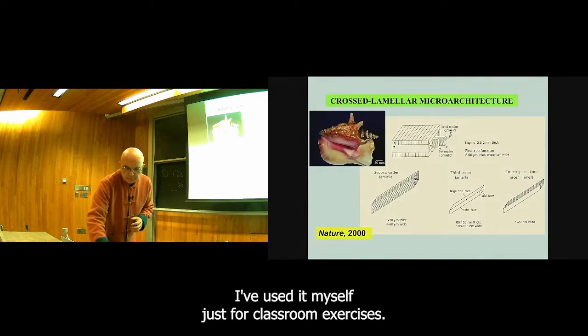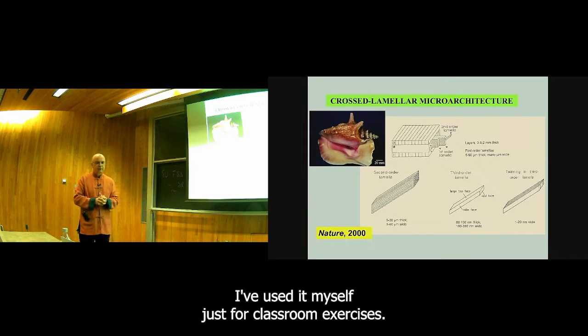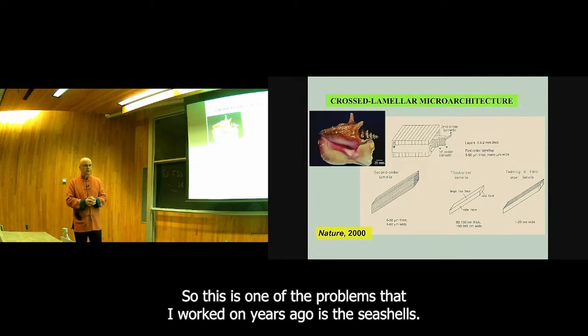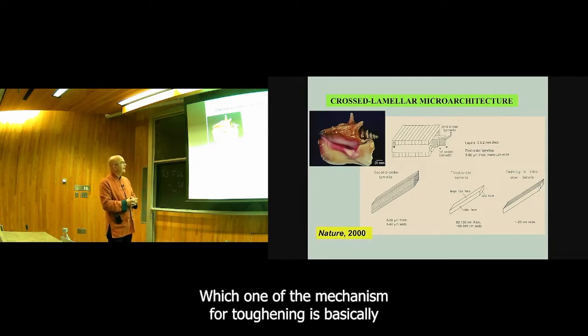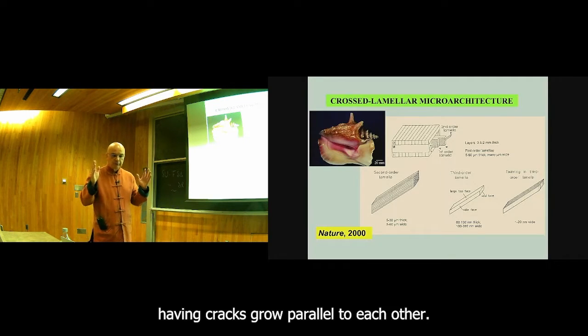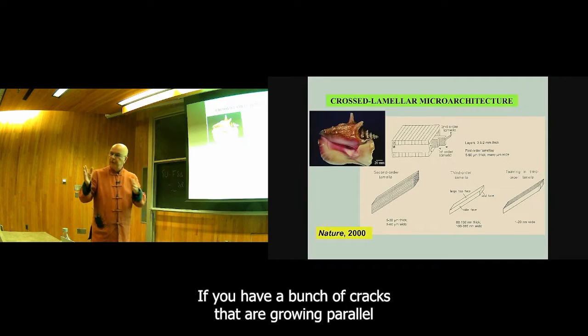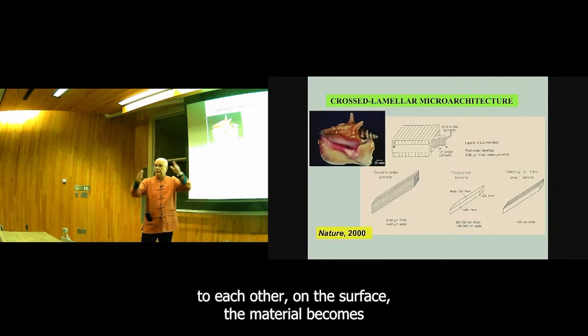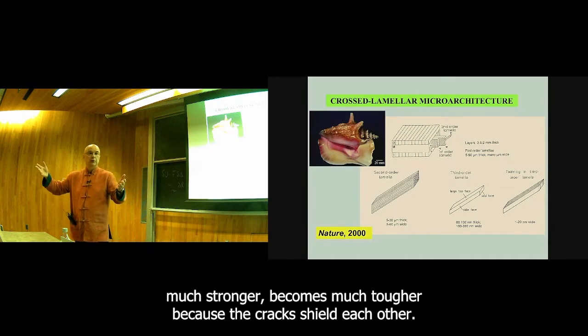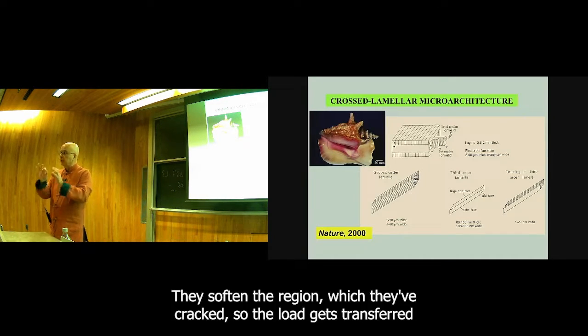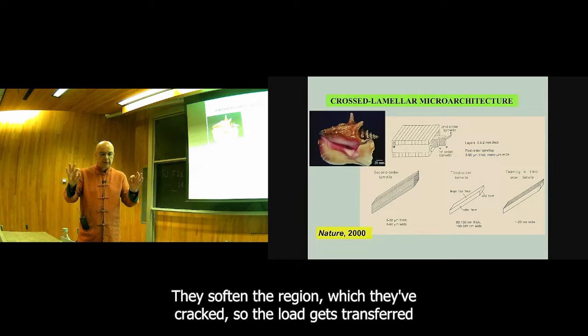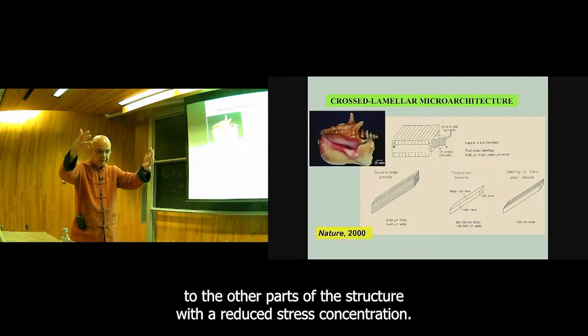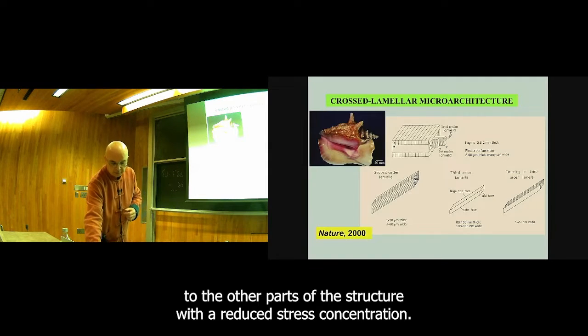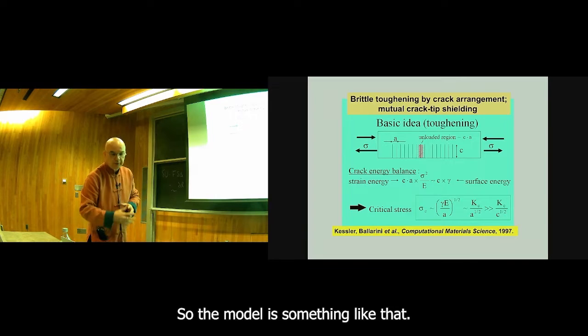How do you use it? I've used it myself just for classroom exercises. You could do quick and dirty calculations. So this is one of the problems that I worked on years ago, these seashells, where one of the mechanisms for toughening is basically having cracks grow parallel to each other. If you have a bunch of cracks that are growing parallel to each other on the surface, the material becomes much stronger, much tougher, because the cracks shield each other, they soften the region which they've cracked, so the load gets transferred to the other parts of the structure with a reduced stress concentration. So the model is something like that.